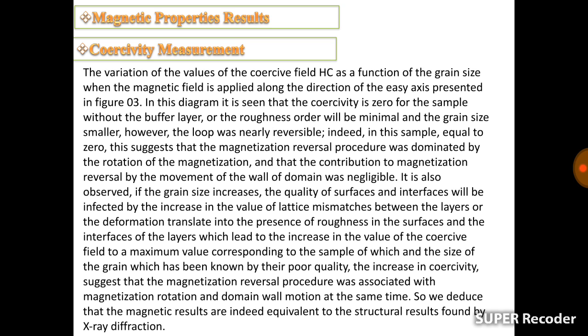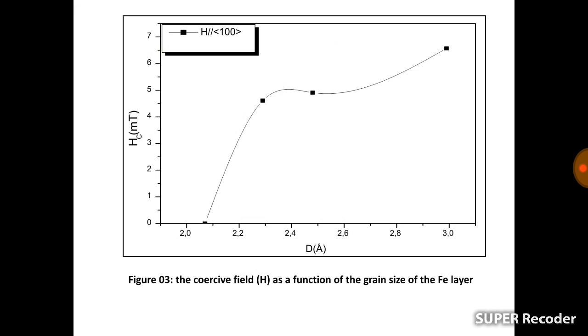Coercivity measurement. The variation of the values of the coercive field as a function of the grain size, when the magnetic field is applied along the direction of the easy axis, is presented in figure 3. In this diagram, it is seen that the coercivity is zero for the sample without the buffer layer, where the roughness order is minimal and the grain size smaller. However, the loop was nearly reversible in this sample, with coercivity equal to zero. This suggests that the magnetization reversal process was dominated by the rotation of the magnetization and that the contribution to magnetization reversal by movement of the domain wall was negligible.